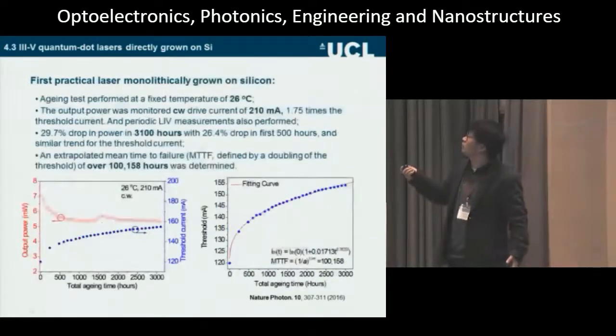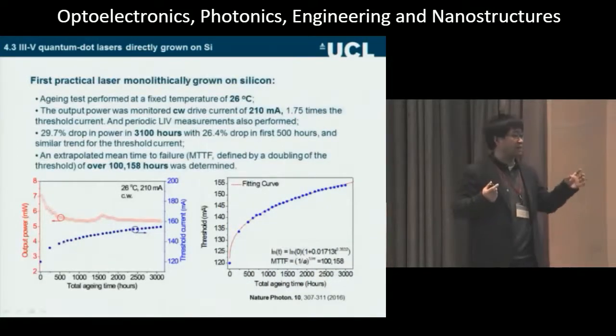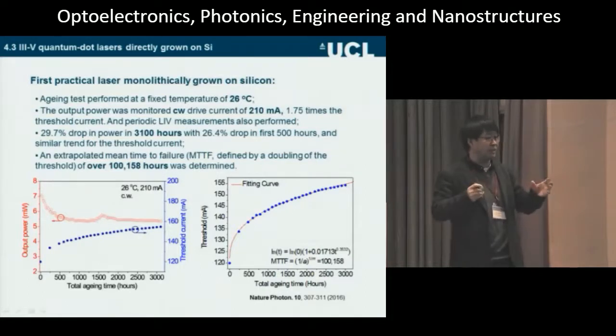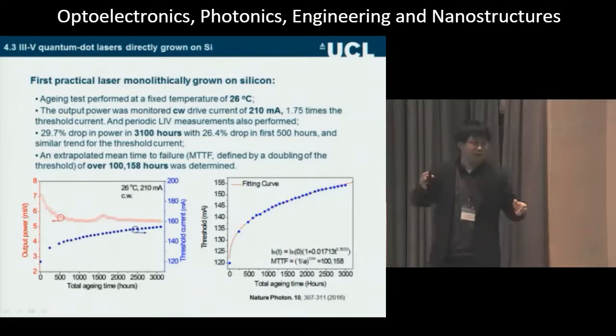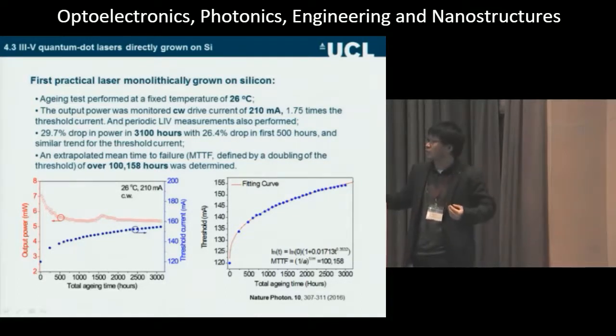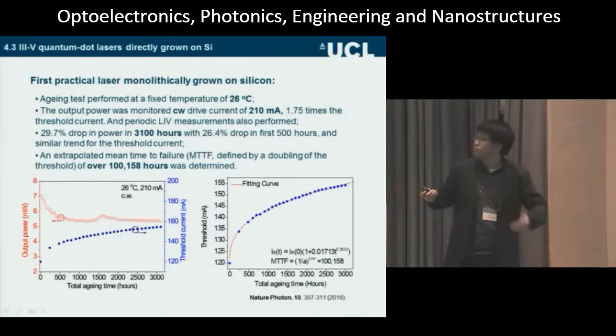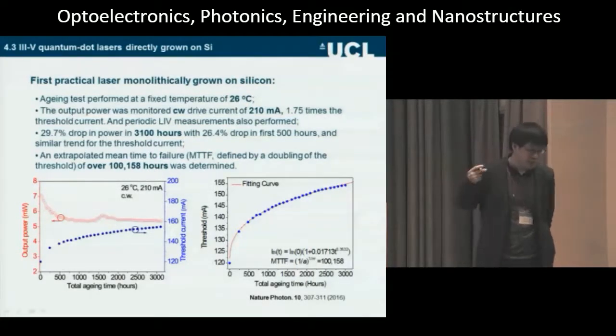Also, for the first time, we do a life test. For this life test, I have to say this device is very big. It's not a commercial device, and not a perfect process. We also don't have an HR coating, so the device is very basic. The lifetime turned out to be a surprise. In the first 500 hours, the power reduced dramatically and the threshold current increased dramatically. After 500 hours, it gets more stable. We measured about 3,100 hours, and the lifetime is predicted to be over 100,000 hours. So that's the first practical laser on silicon.